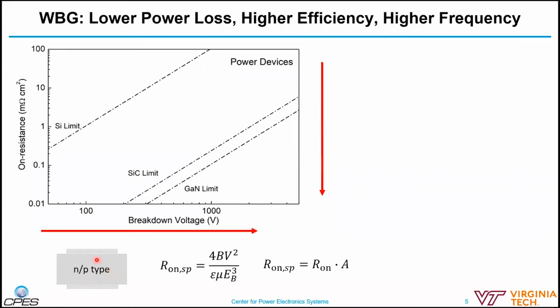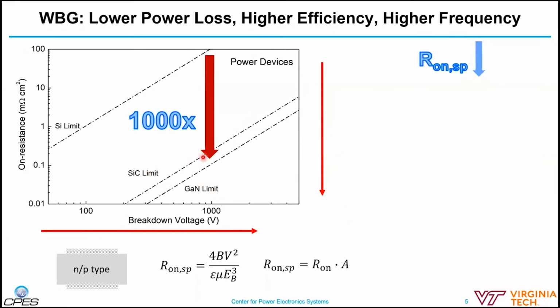It turns out that this trade-off between on-resistance and breakdown voltage is related to the semiconductor material properties. This is the silicon limit. This is the silicon carbide limit. This is the gallium nitride limit. For example, if we compare the gallium nitride limit with the silicon limit, for the same breakdown voltage, let's say 1,000 volts, gallium nitride devices can achieve about 1,000 times lower specific on resistance. So how does this 1,000 times lower specific on resistance impact the device and system performance?